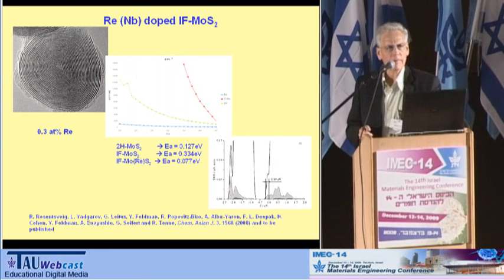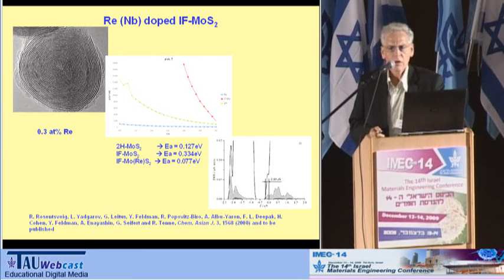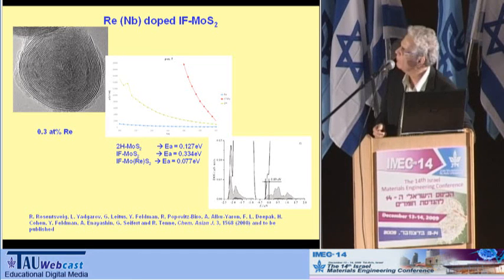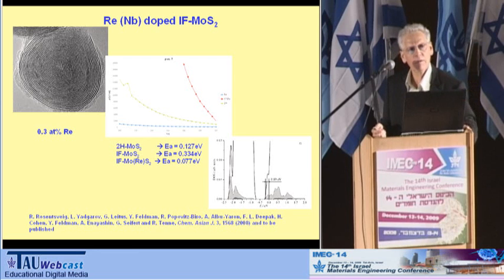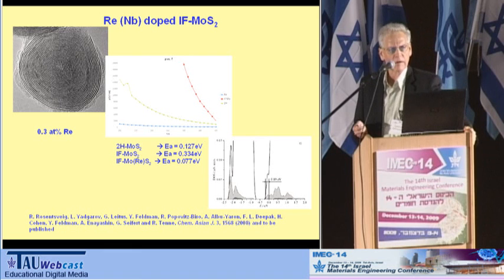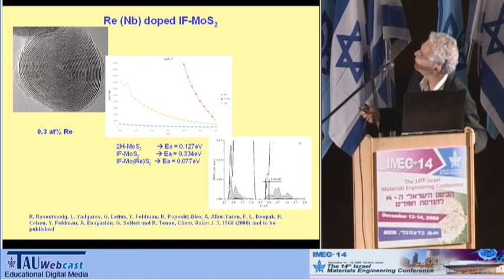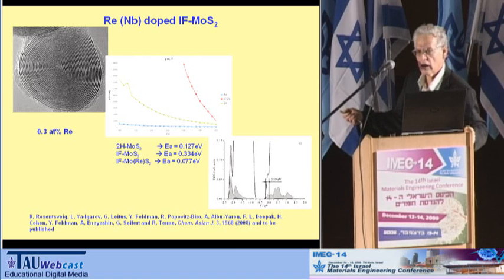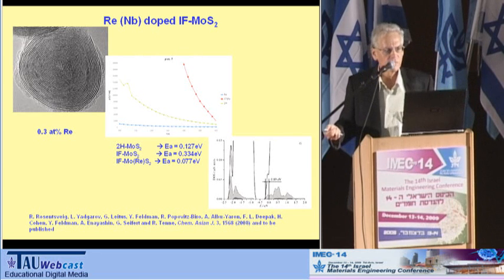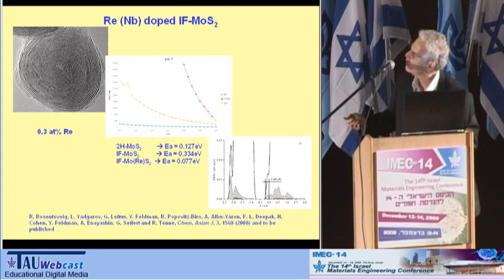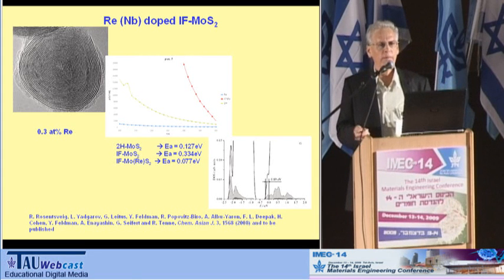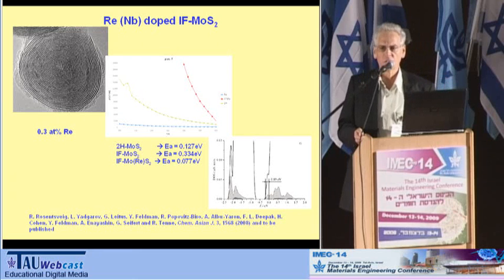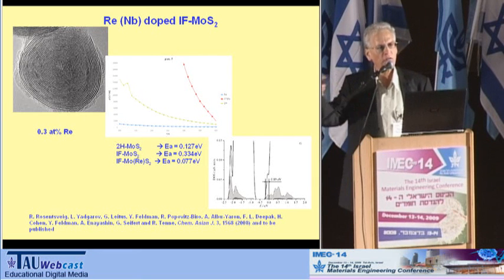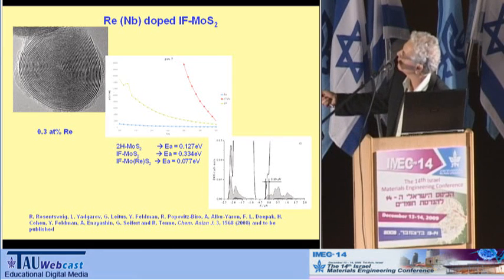Recently we were able to dope them, using different techniques. In this case we dope them with rhenium. We dope them also with niobium. The idea is to introduce minute quantities of rhenium in order to make these nanoparticles conductive. You see, they look the same, but they have a fraction of a percent of rhenium in the structure. The rhenium substitutes for molybdenum. Since rhenium has one extra valence electron, it donates this electron to the conduction band, and the material becomes extremely conductive.